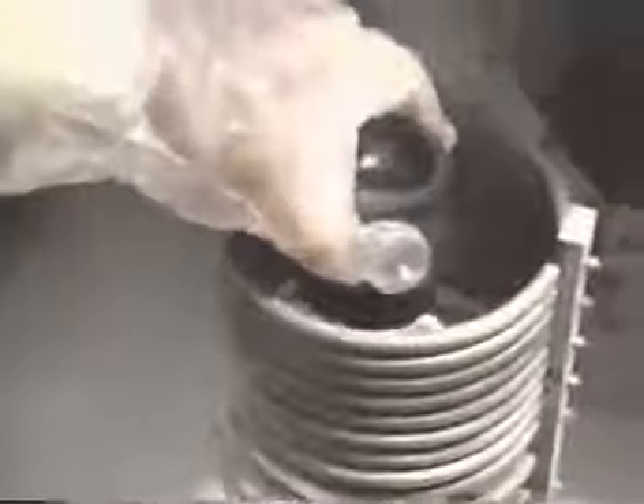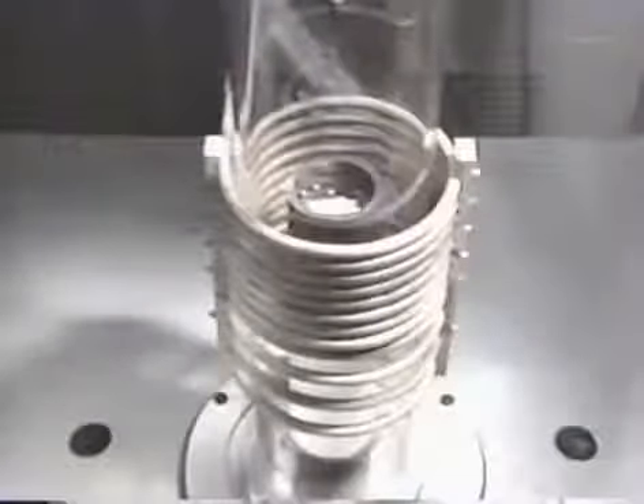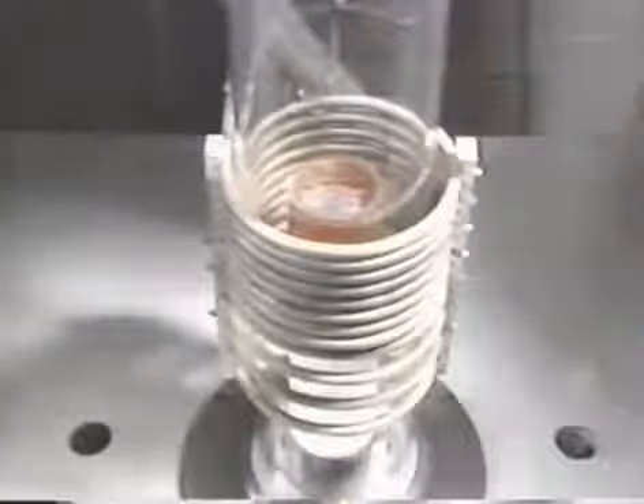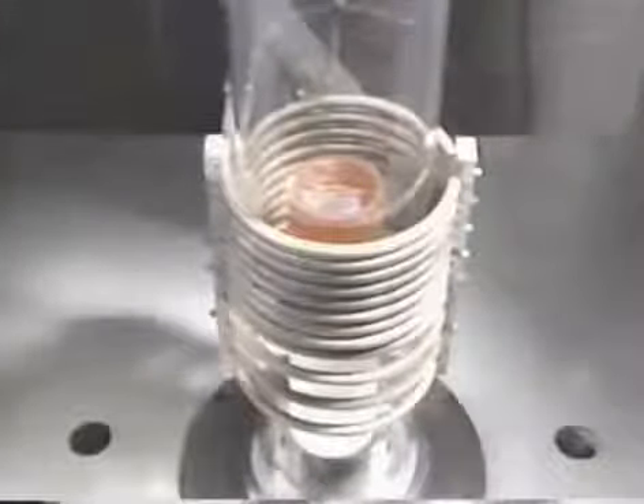We had the single crystal making process reenacted at Tohoku University. We placed germanium crystals with a raised degree of purity in a crucible, which we then set inside a furnace. We fit seed crystals for making them into single crystals to a rotating rod. We then seal the furnace and inject an inert gas. When we send a high-frequency electric current through the heating coil wrapped around the quartz tube, the germanium inside melts.